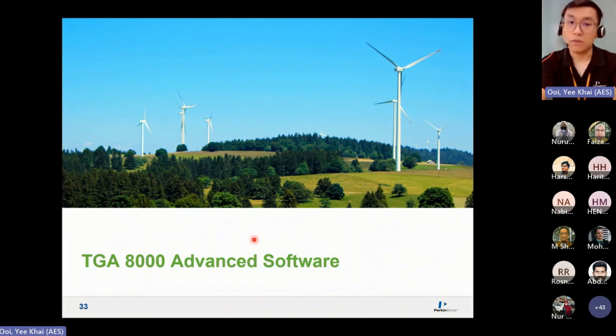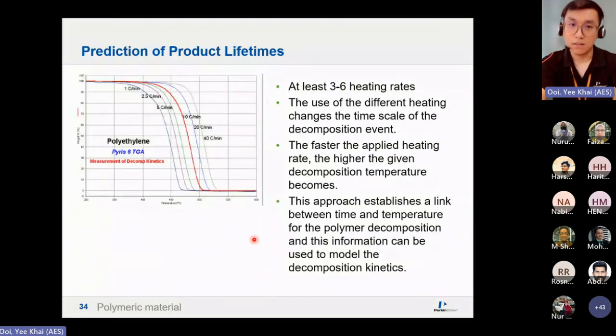For TGA 8000 only, there's advanced software. What this does, as I mentioned just now, is that you can do kinetics. We have a 6 curves method at different heating rates, so only one-step heating. This is a polyethylene material. This is what the TGA kinetics, or the decomposition curves, look like. Six different heating rates, or minimum 3 if you are going to run a kinetic analysis. So monitor the decomposition events using the time scale as well.